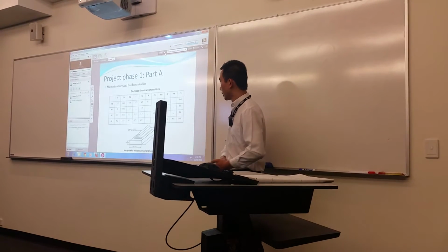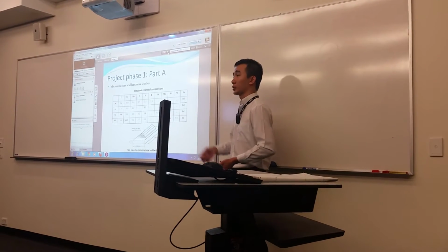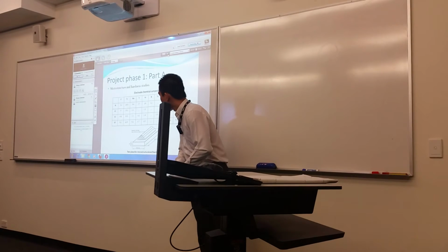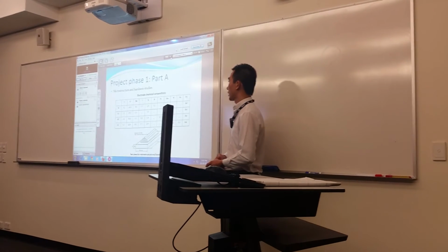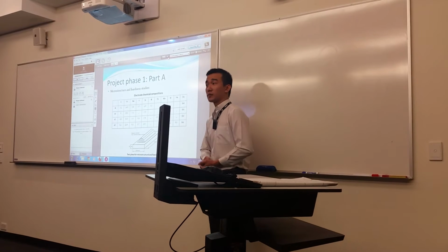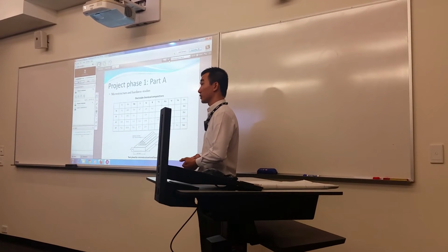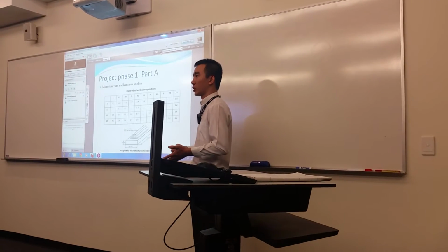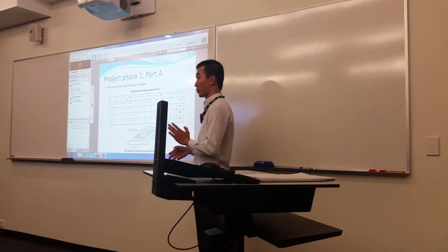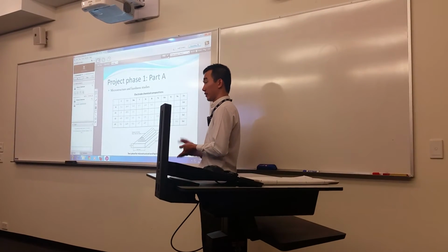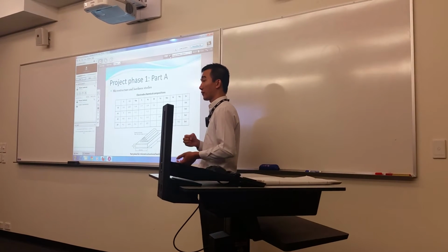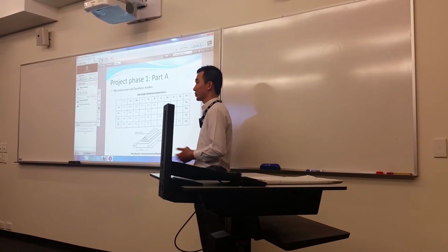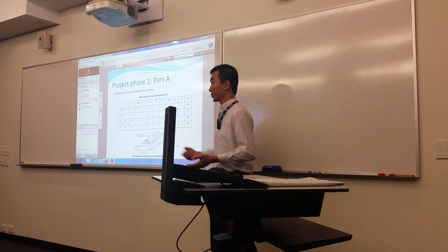On the screen now, you are seeing the table showing the chemical composition of the electrodes used in my research. As can be seen, they all have a high content of carbon and chromium. This is very important because it is beneficial for the formation of a compound named carbide. Carbide is a compound formed between carbon and another element, in this case chromium, which has a much higher hardness compared to the normal matrix of the materials, and that provides the hardness of the materials.